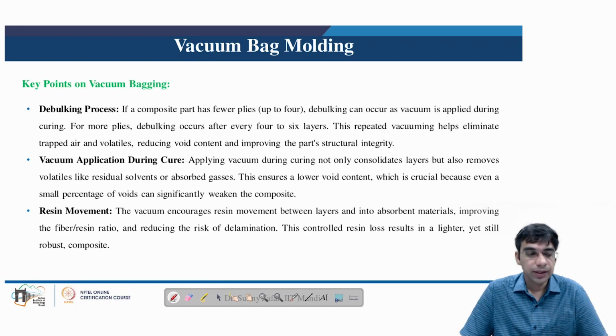We will see some of the key points in the vacuum bagging process. The first key point is the debulking process. Debulking is used, for example, if a composite part has few plies, say up to 4, debulking can occur as vacuum is applied during the curing. For a larger number of plies, debulking occurs after every 4 to 6 layers. This repeated vacuuming helps to eliminate trapped air and volatiles, reducing void content and improving the part's structural integrity.